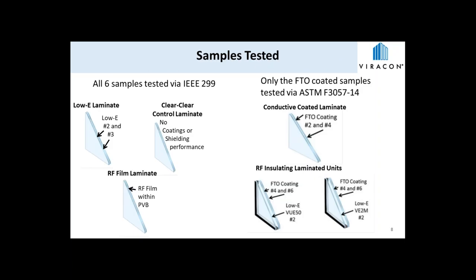So there are six different samples tested altogether within the IEEE method, four laminates and two laminated units. The three samples on the left were specifically tested within the IEEE method, where the three samples on the right were tested both under the IEEE method and the ASTM method. As mentioned earlier, the low-E laminate, the furthest left-hand side, consists of the two coating layers, both within the laminate.